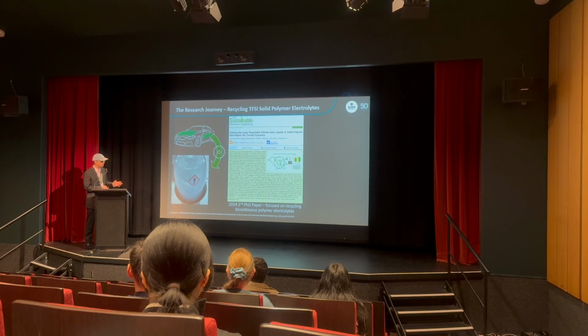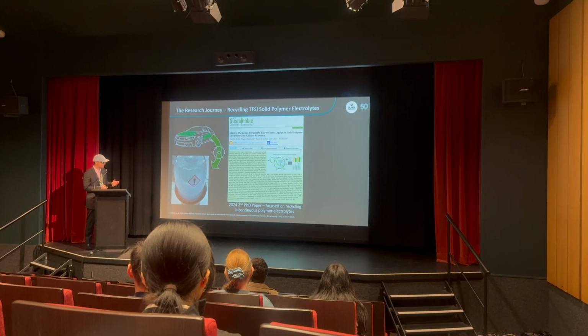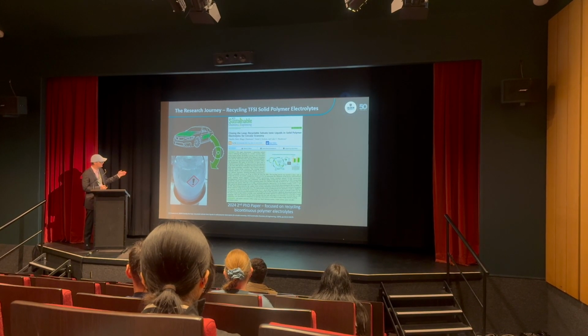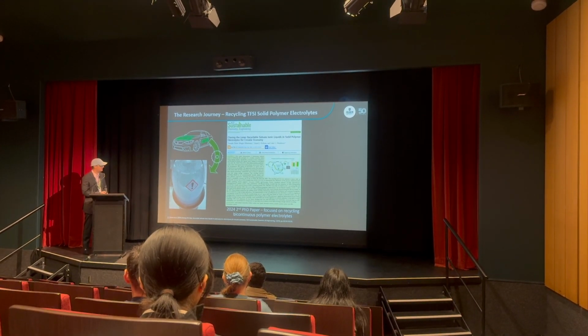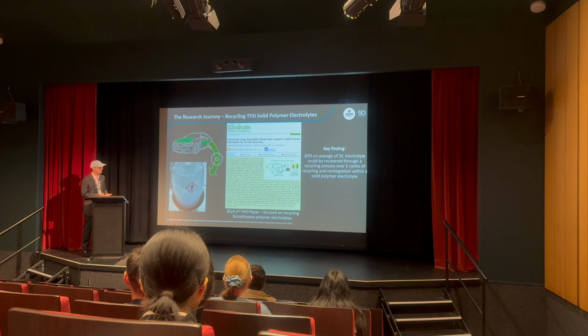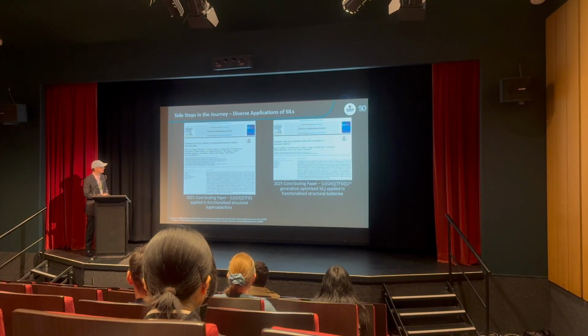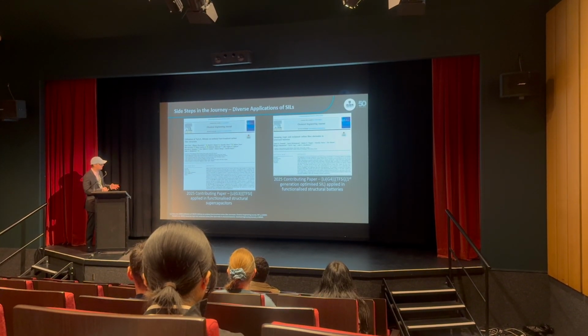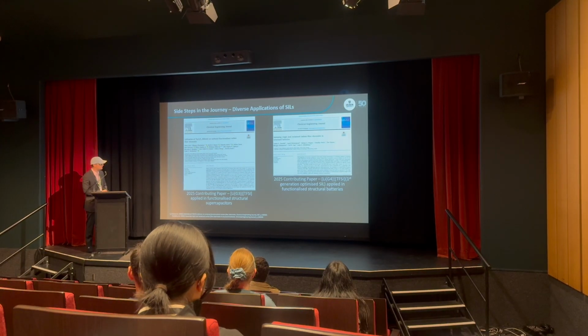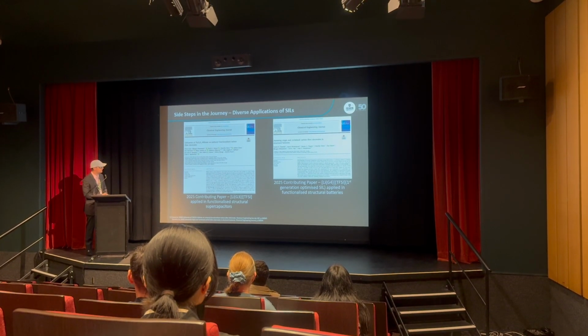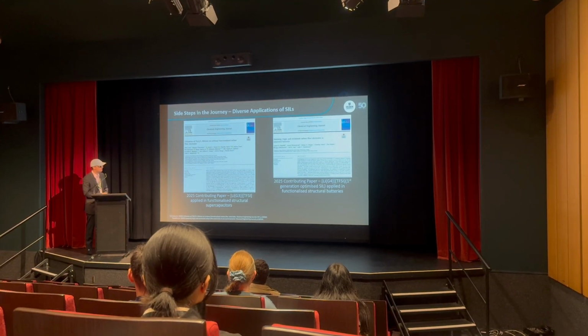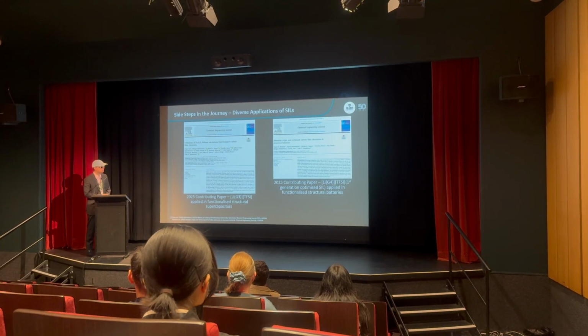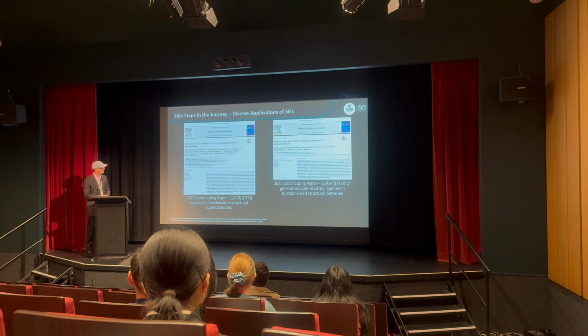There was a bit of a side step in the process where we looked at whether we could recycle these solid polymer electrolytes, and one of the favourite parts of my PhD was using a NutriBullet fruit blender to blend up some solid polymer electrolyte. The key finding of this was that we could recover 83% of the ionic liquid that was put into the system over 5 cycles on average. We had a few side steps in the journey where we applied the traditional G3 TFSI lithium Solvate Ionic liquid in a capacitor device, and then we also applied an optimized first generation Solvate Ionic liquid in a prototype structural battery with carbon fibre, which was very exciting.